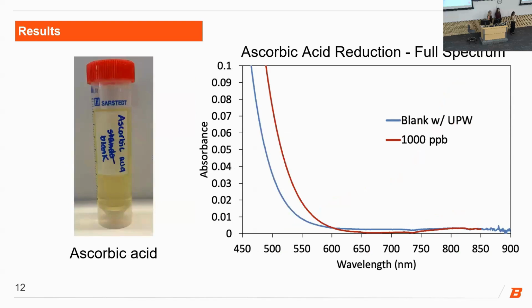On the other hand, with our second set of samples, we use ascorbic acid as our reducing agent, and instead of turning blue, it turned yellow. And we think that this happened because there was incomplete reduction. And when we look at the full spectrum, we don't see any absorbance peaks, which further confirms that the reduction was incomplete. In other words, we didn't reach the endpoint for it to change colors.